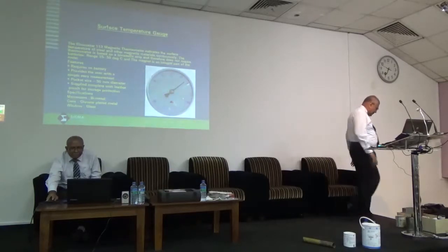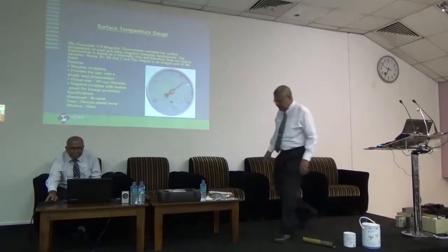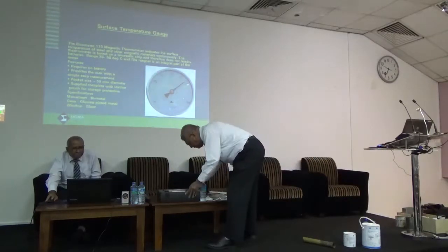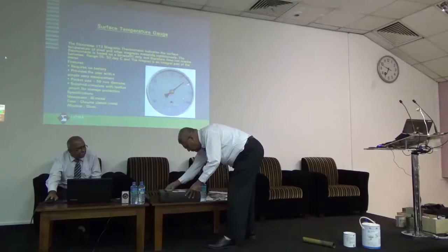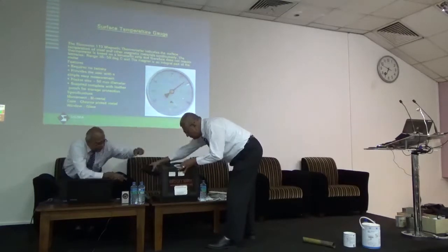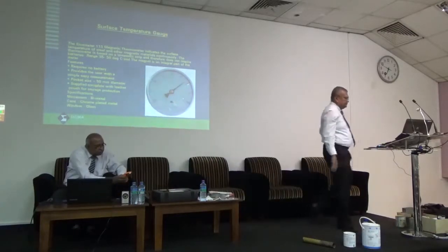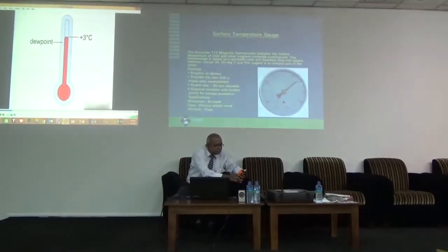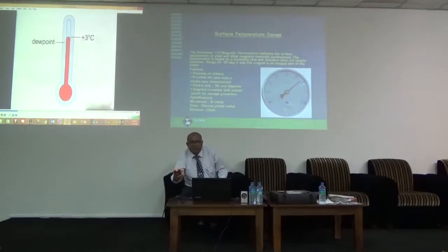Steel temperature is an important factor of coating application and coating cure. For this reason, the steel temperature must be checked before the coating is applied and during any curing process, particularly where a hot cure is specified. Check the specification for the exact criteria on steel temperature, but as a rule of thumb, ensure the steel temperature is at least 3 degrees centigrade above the dew point.